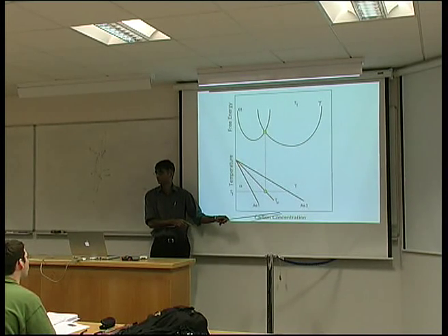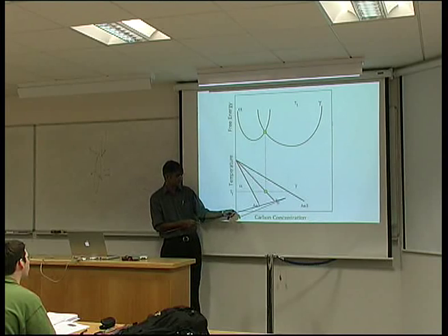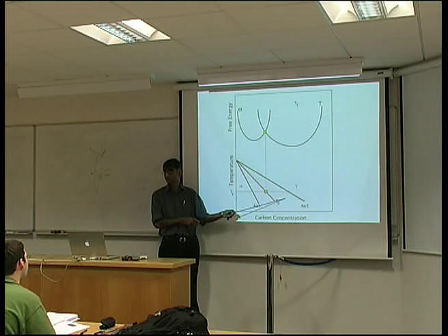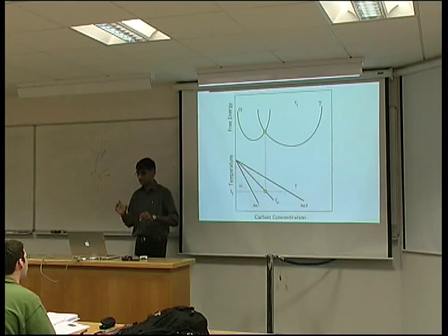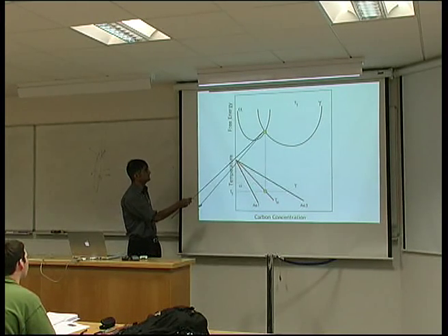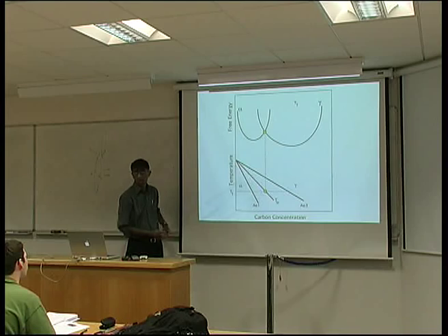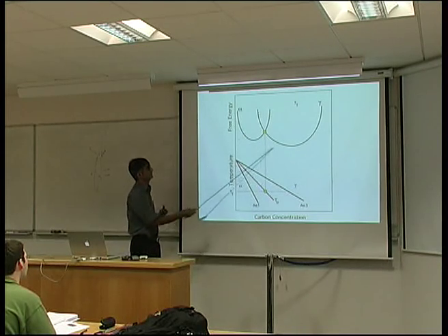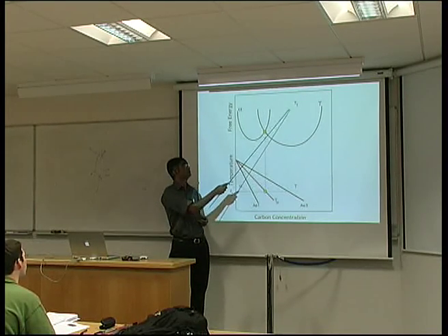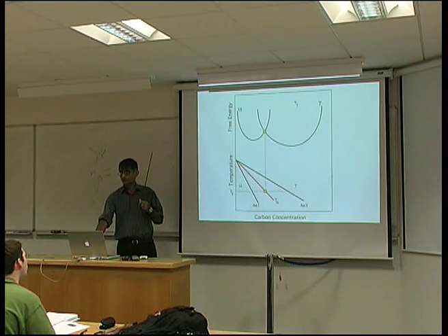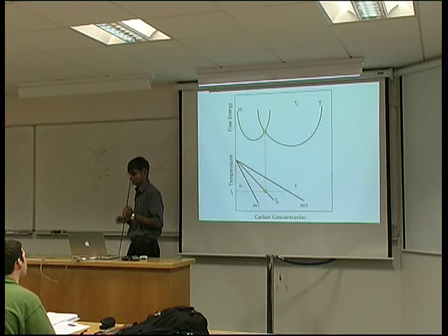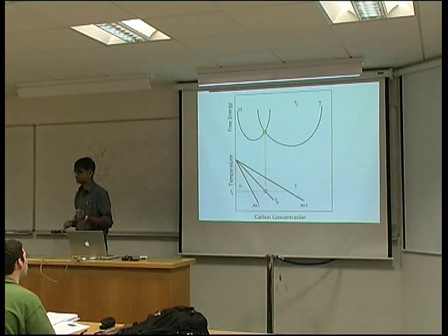Everybody happy with that? If I have austenite of this composition, it's thermodynamically impossible to get diffusion-less transformation. So the locus of these points as a function of temperature gives me the T0 curve, because this is for a particular temperature T1. Okay, so if the carbon concentration of the austenite exceeds the T0 curve, it's impossible to get diffusion-less transformation.